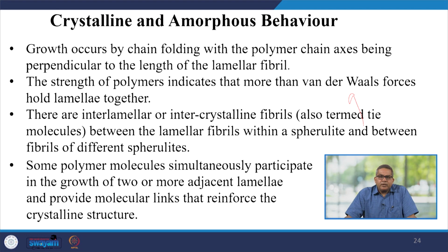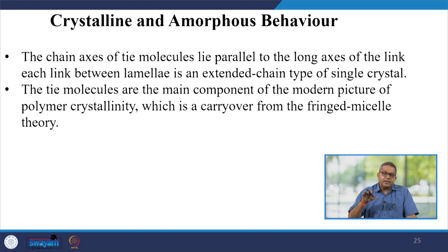Now, the strength of the polymer indicates that more than van der Waals forces hold the lamellae, and these are interlamellar or intercrystalline fibrils. They are also termed tie molecules between the lamellar fibrils within the spherulite and between the fibrils of different spherulites. Some of the polymer molecules simultaneously participate in the growth of two or more adjacent lamellae and provide molecular links that reinforce the crystalline structure. So, the chain axis of the tie molecule lies parallel to the long axis of the link. Each link between the lamellae is an extended chain type of single crystal. The tie molecules are the main component of the modern picture of polymer crystallinity, which is a carryover from the fringed micelle theory.